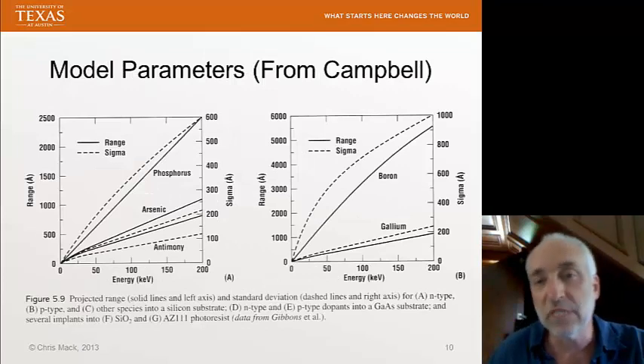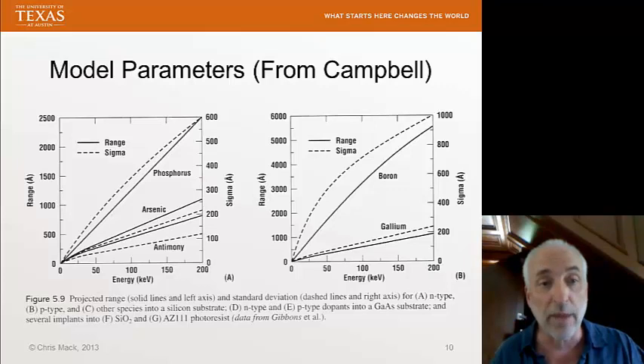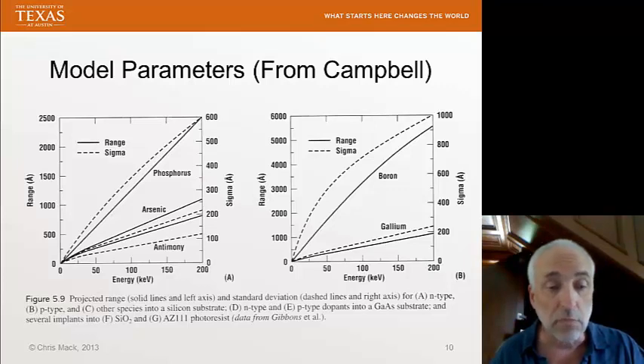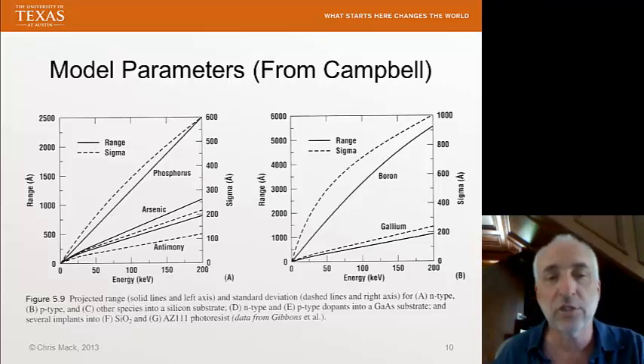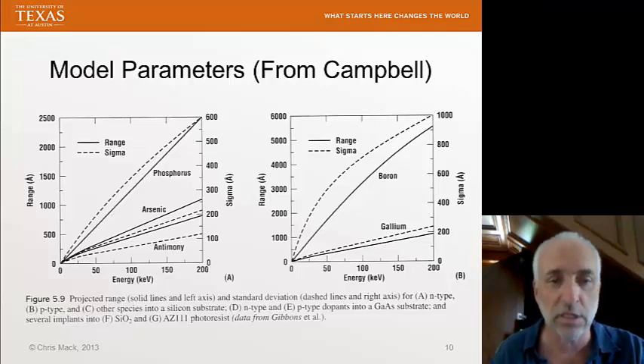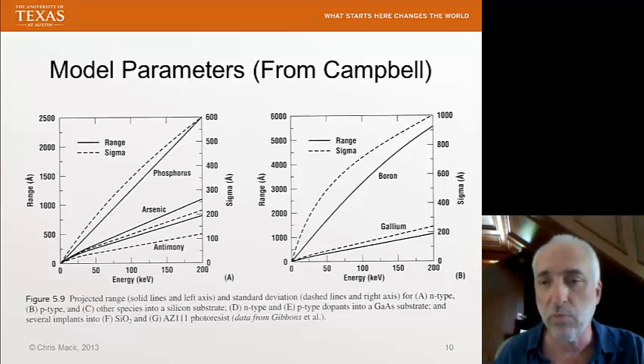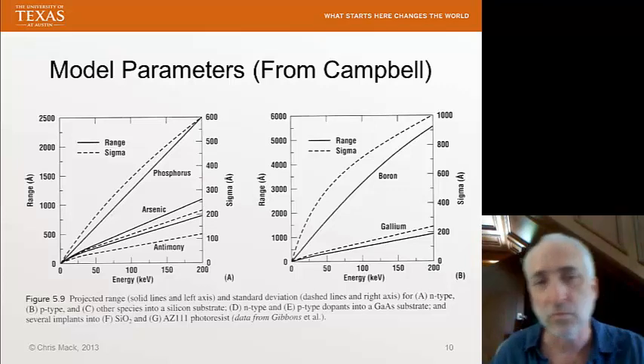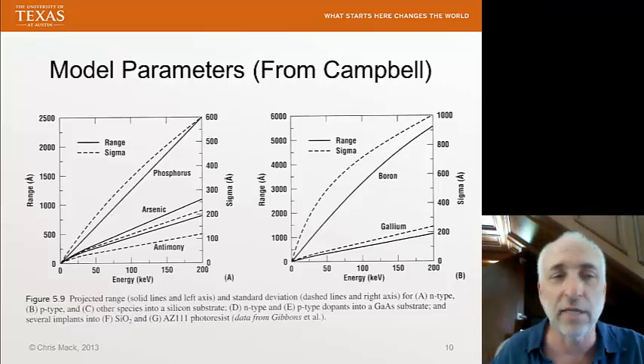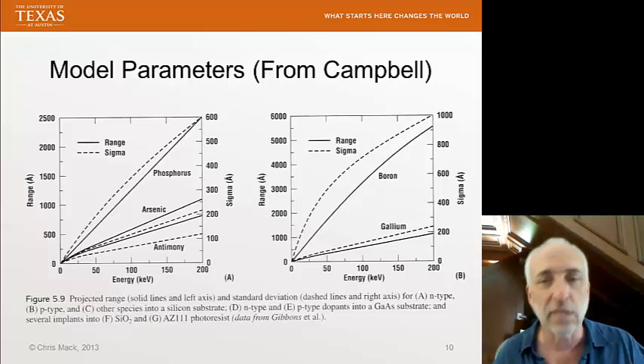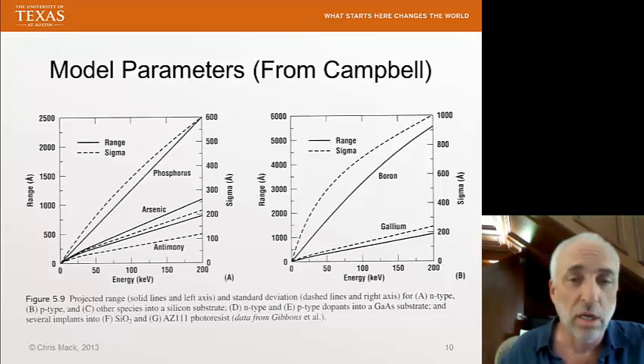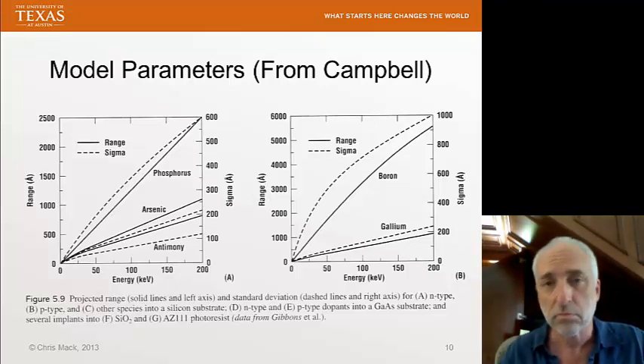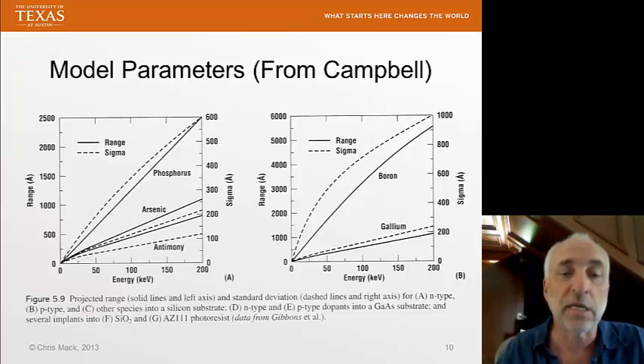Here are some examples of experimental model parameters — projected range (labeled as 'range') and straggle (labeled as sigma of the Gaussian) — for phosphorus, arsenic, and antimony (the N-type dopants) and boron and gallium (the P-type dopants). Comparing the scales of sigma and range, you can see that the sigma is typically about a quarter of the range. These graphs come from the Campbell textbook.